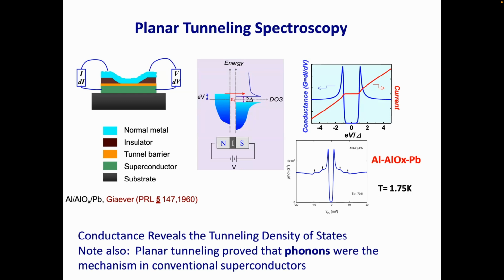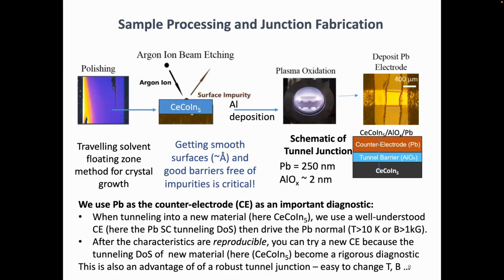And you've all seen these graphs. But what I want to show you is on the lower bottom right there. Here's just an example from our lab that shows aluminum with aluminum oxide as the tunnel barrier and lead as the counter electrode. And what we see here are those little bumps. Those little bumps are the 6 and 8 millielectron volt phonons from the lead. That's what was proved by McMillan and Rowell, that it was strong coupling lead phonons that caused the pairing. So one of the other take-home messages is that if you don't see the bosonic excitation in the tunneling, the electrons aren't feeling it. If they're not feeling it, they're probably not having to do with the pairing mechanism. So these are the very simple take-home messages without getting fancy.